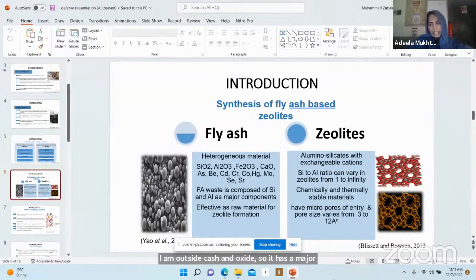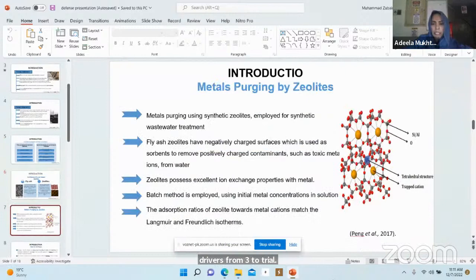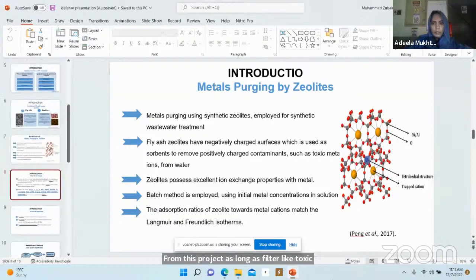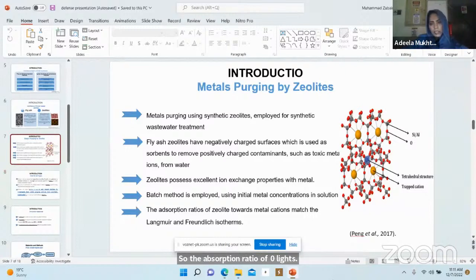Zeolites are aluminosilicates with exchangeable cations. They are thermally and chemically stable. They have micropores, and their pore size varies from 3 to 12 angstrom. So synthetic zeolites are used for metal purging in wastewater treatment. Fly ash-based zeolites have negatively charged surfaces, which is used to remove positively charged contaminants from wastewater, like toxic metals. Zeolites possess excellent ion exchange properties with metals. So the adsorption of zeolites toward metal cations matches Langmuir and Freundlich isotherms.